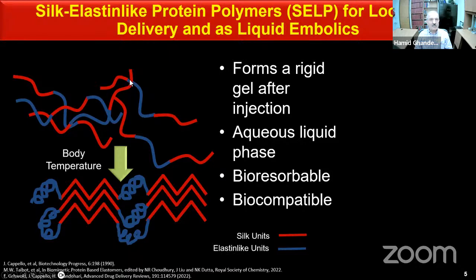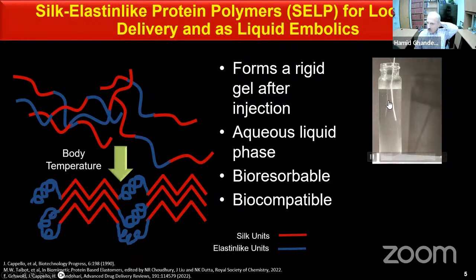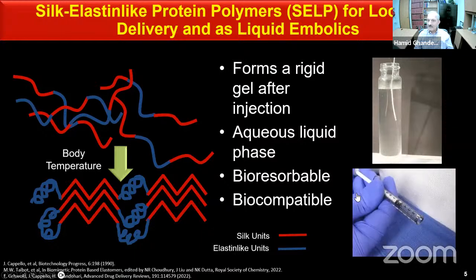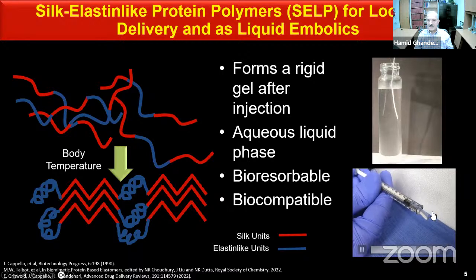So if you could imagine, the blue segments here are the elastin portions. The red segments are the silk portions. As you increase the temperature from, let's say, room temperature to body temperature, these elastin blocks collapse. They bring the silk units closer together. They hydrogen bond, and they form hydrogel material. So this is shown, for example, as you deliver these polymers at higher temperature, they start to form a turbid solution. And in the next iteration, you can see that you can nicely get hydrogels out of these systems,